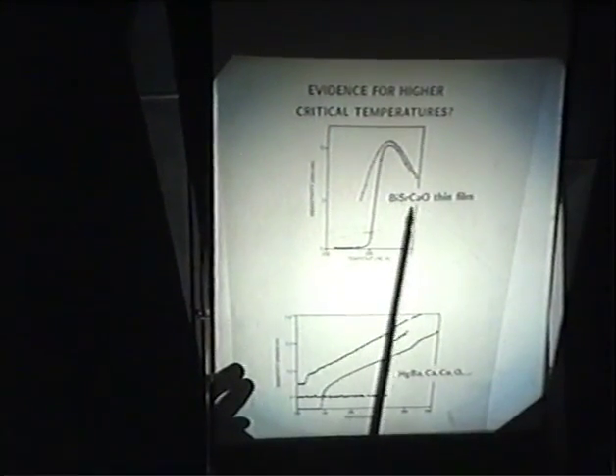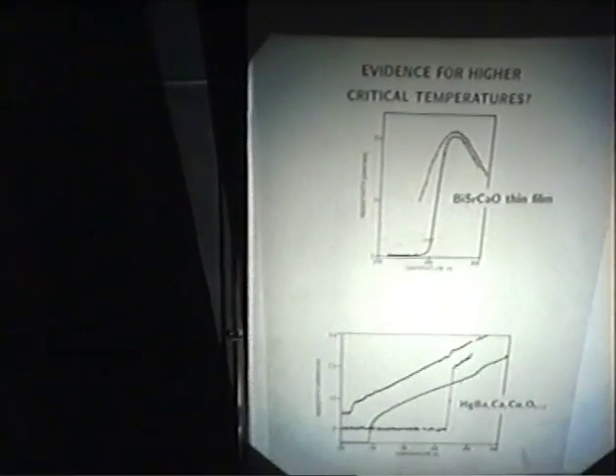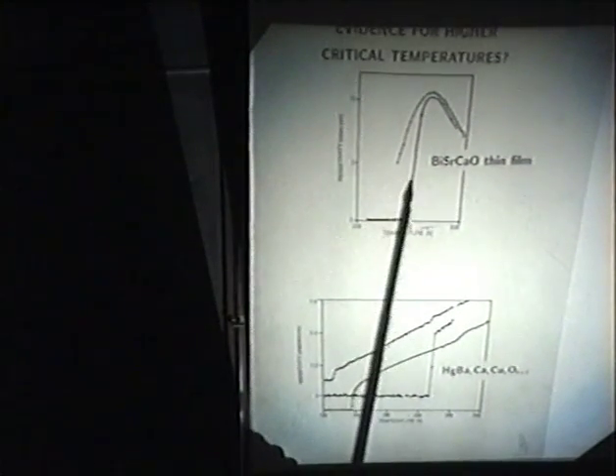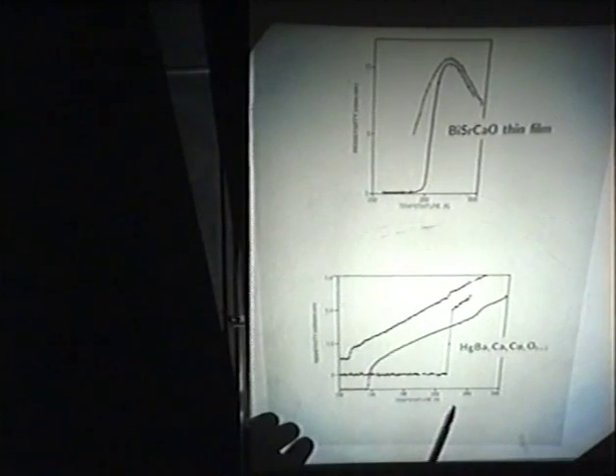Well, if you look in the scientific literature, hardly a month goes by without a diagram something like this. Professor XYZ from University ABC has a bismuth strontium calcium oxide film, and when he cooled it down, it went superconducting at 250 Kelvin. Astounding. He then warmed it up and cooled it down again and didn't do it anymore. Another situation for the Journal of Irreproducible Results.